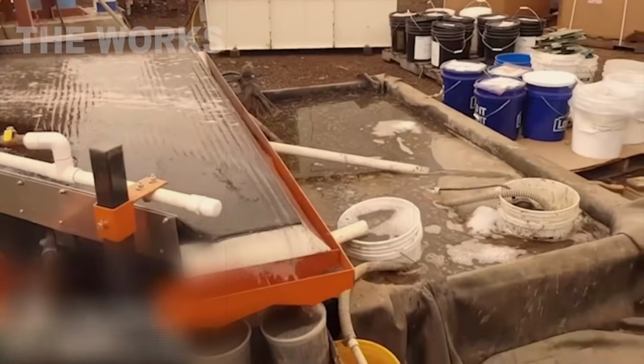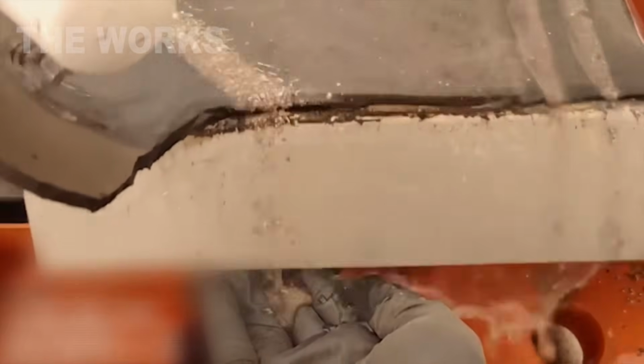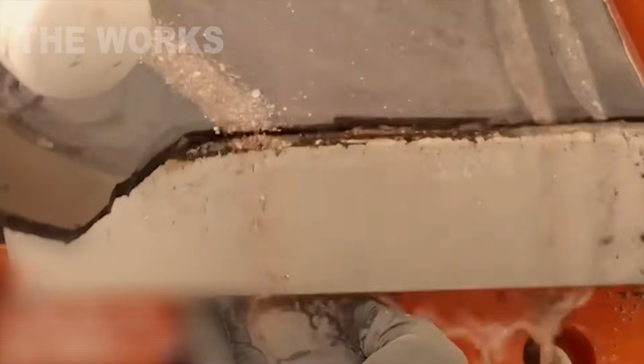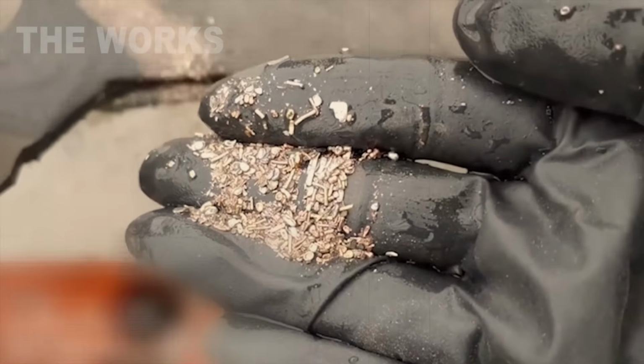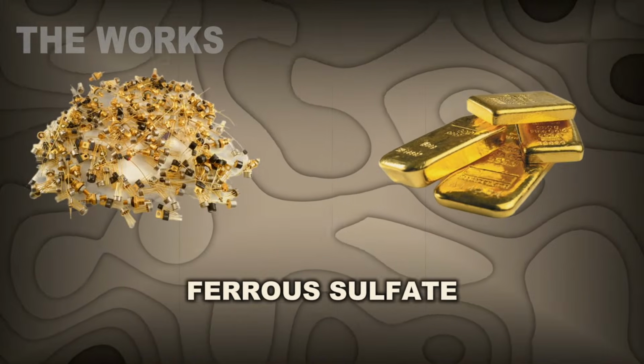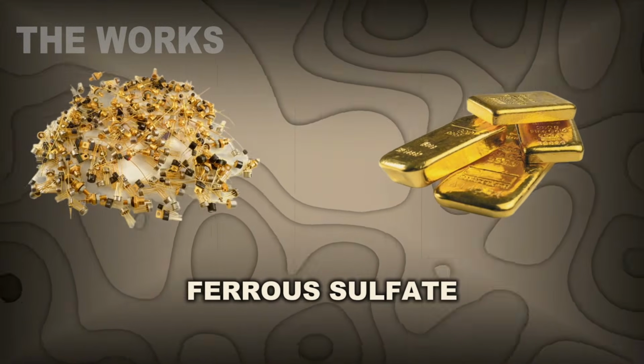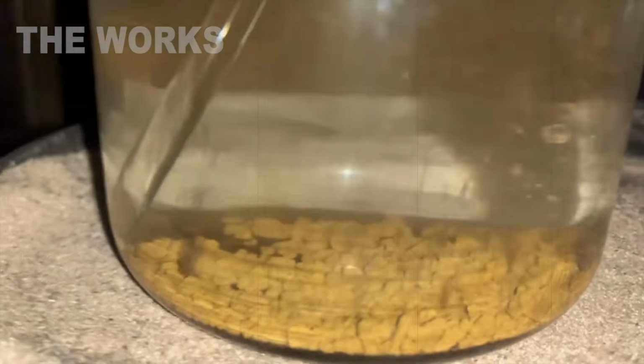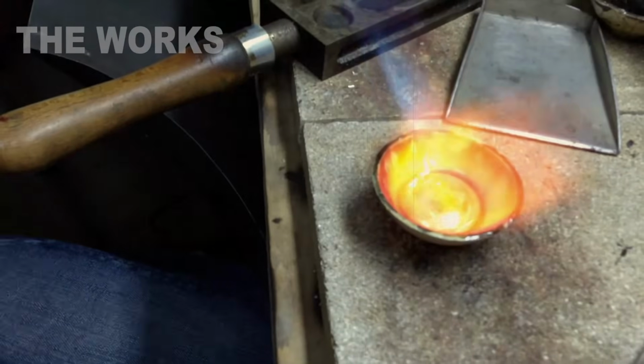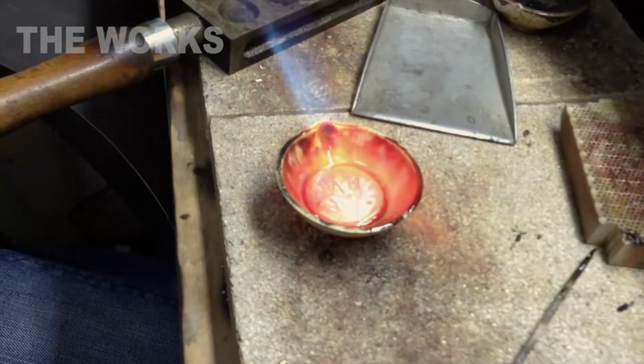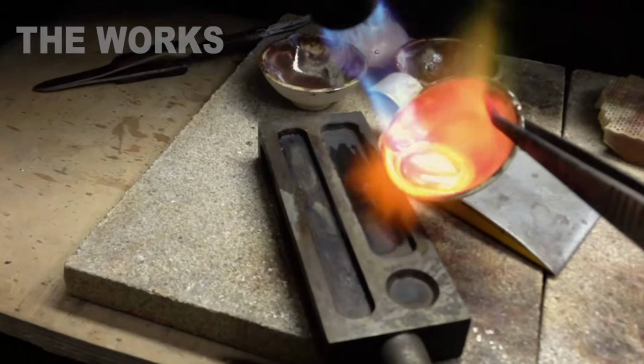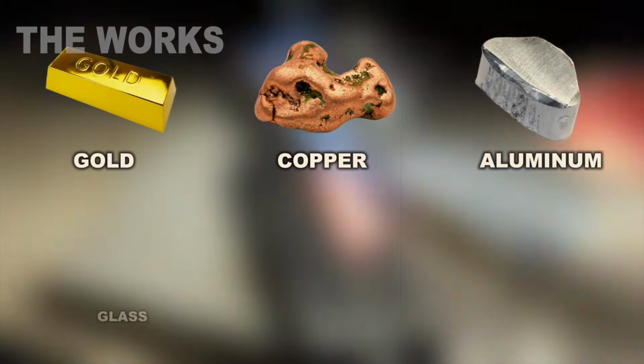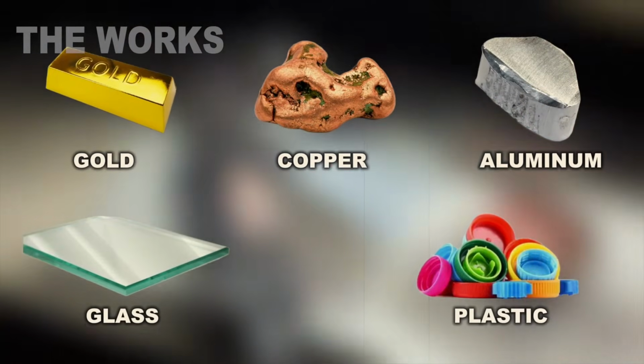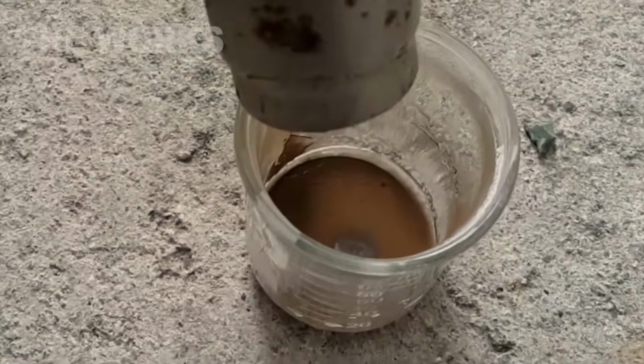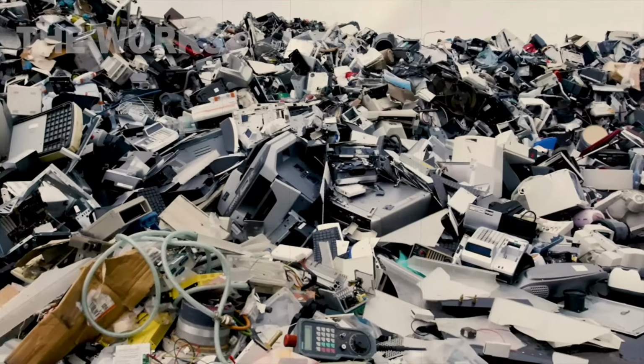After the precious metals have dissolved into the solution, the precipitation process begins. Special chemical substances are added to the liquid, which cause the pure metals to fall out as sediment. For instance, ferrous sulfate is used to precipitate gold. This gold sediment is then thoroughly washed, dried, and remelted into small but incredibly valuable ingots. Similar methods are employed to extract copper and silver, though using different, less aggressive acids or the electrolysis method. In the final stage, all the recovered materials, gold, copper, aluminum, glass, and plastic, are compressed into compact blocks.